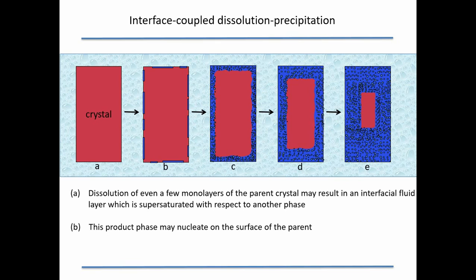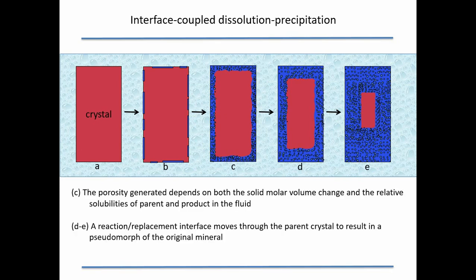we may supersaturate the fluid at the interface with respect to a new phase. It doesn't matter what's in the ocean, in the fluid away from the surface. It's that fine layer at the interface that controls the whole process. And that will be very different because of dissolution compared to the original solution. And then we progressively go through. I can go on to the next one.